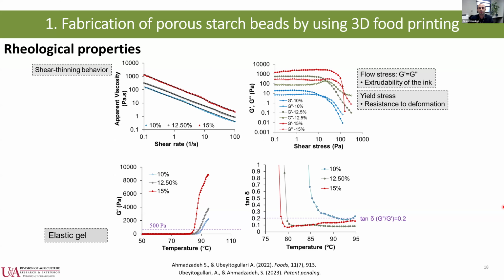So one thing that's very important when you do 3D food printing is the rheology. So the rheology really dictates how stable your print is, or what concentrations you need to use to obtain something that has a good shape fidelity. And that's why we really look into rheological properties when we do 3D printing. So one thing here that we look at, and probably is important to obtain good 3D printing, is shear thinning behavior, so that as you apply more shear during printing, which is basically you have a cartridge and then it goes through a nozzle, right?